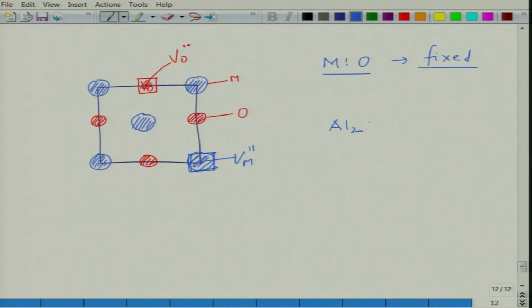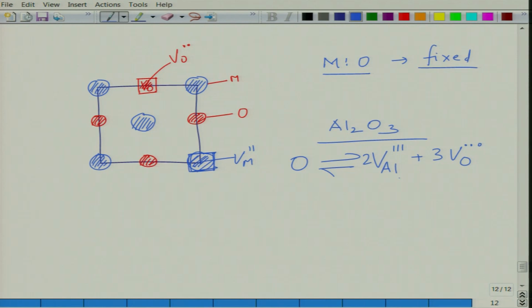Suppose you wanted to do it for Al2O3. For Al2O3, you can write a reaction as 0 equals. Here you can see the stoichiometry is 2:3, which means you will have 2 vacancies of aluminium plus 3 vacancies of oxygen. So you can see you have site neutrality, mass conservation, and charge conservation. You have 6 negative and 6 positive charges.